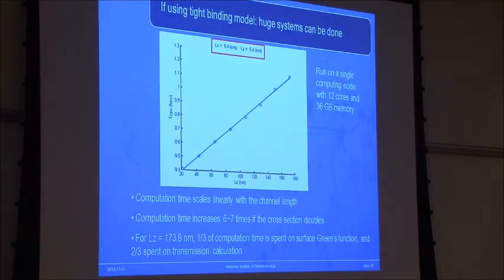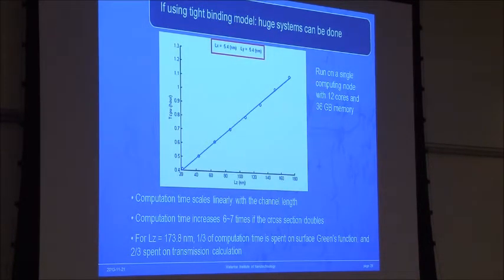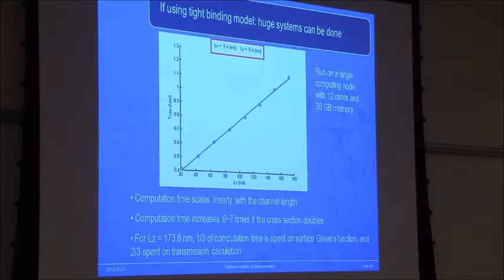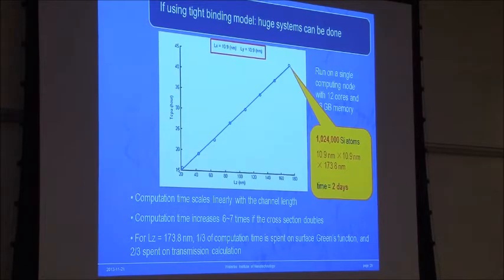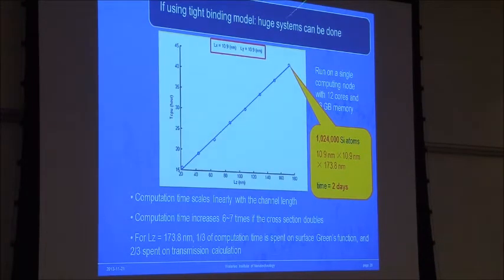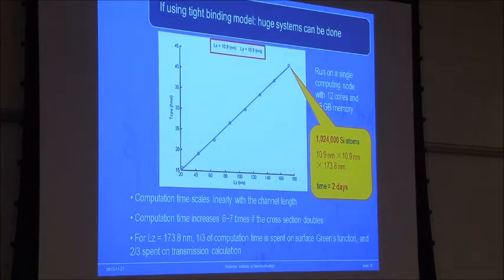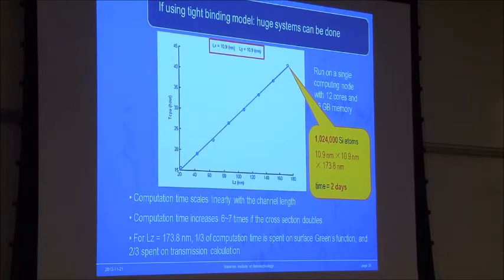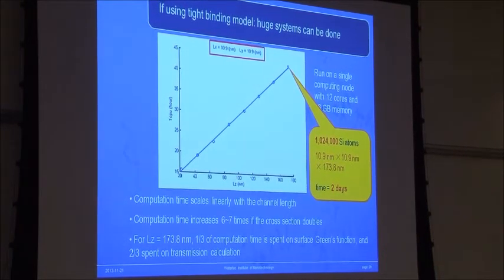Because we can never go to 1 million atoms this way, we also developed tools to generate tight-binding parameters. With tight-binding parameters, you skip the self-consistent loop, and then you can do much larger systems. We can solve 1 million atoms within a day or two, or now actually a day. We can solve this transport problem of a structure with 1 million atoms, 10 orbitals per atom, non-self-consistently. So this is some kind of progress.